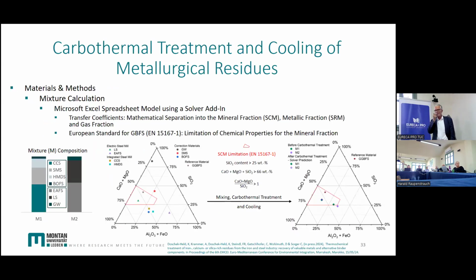So here's the principle. In this triangle diagram, you see the composition of the materials we are talking of. The reference material is this little star you can see here in this red marked area, and the red marked area is the desired area where the composition of our material should lie. All the other slags and correction materials are lying somewhere in the triangle.